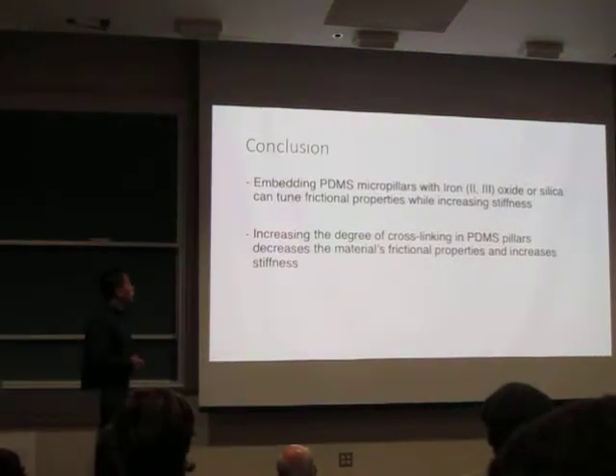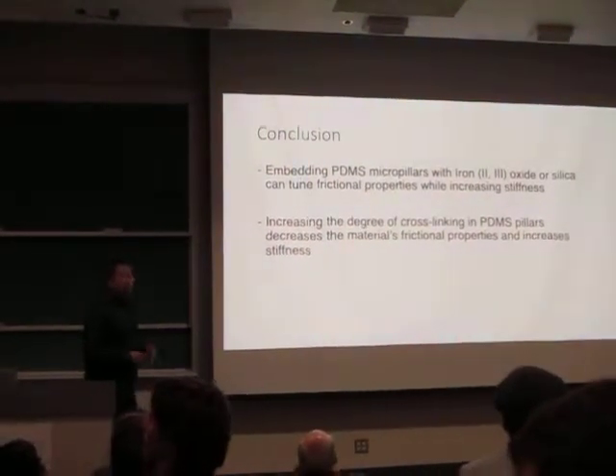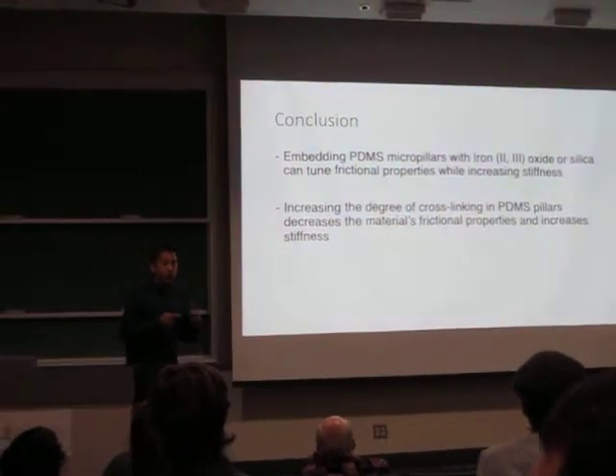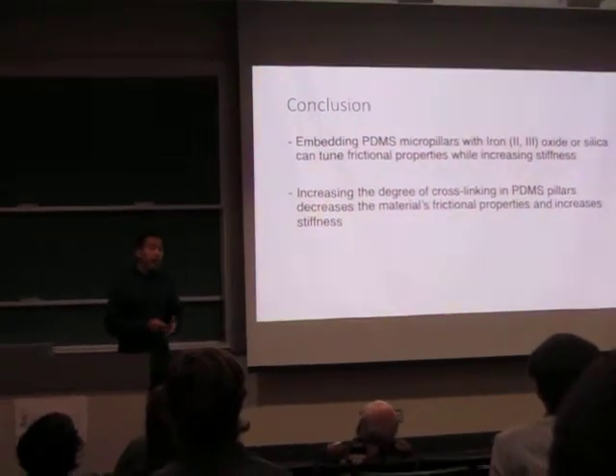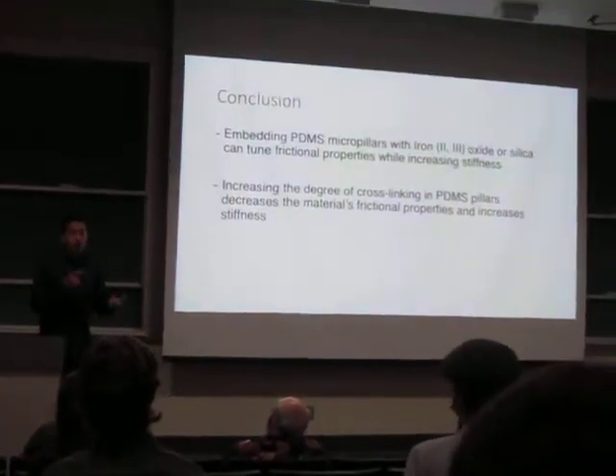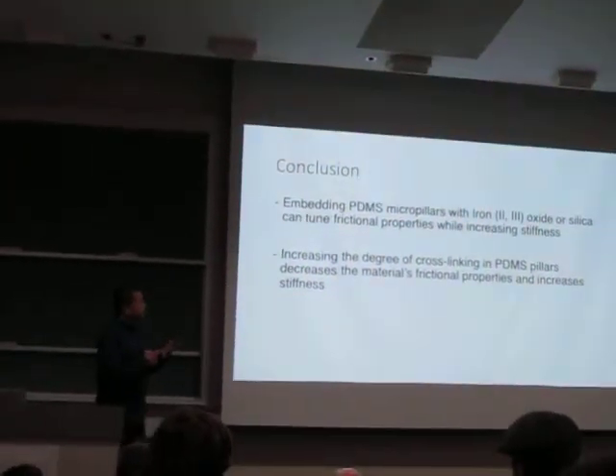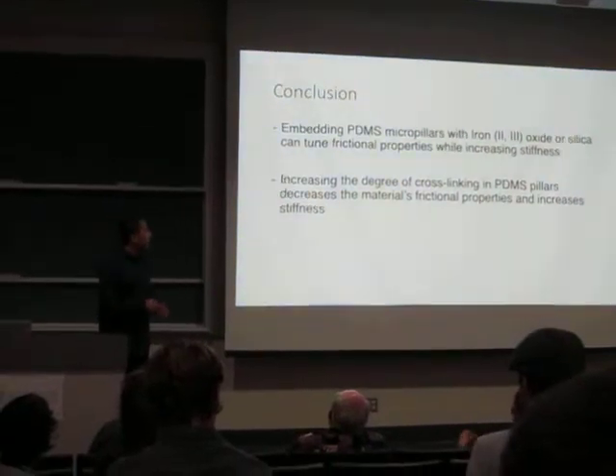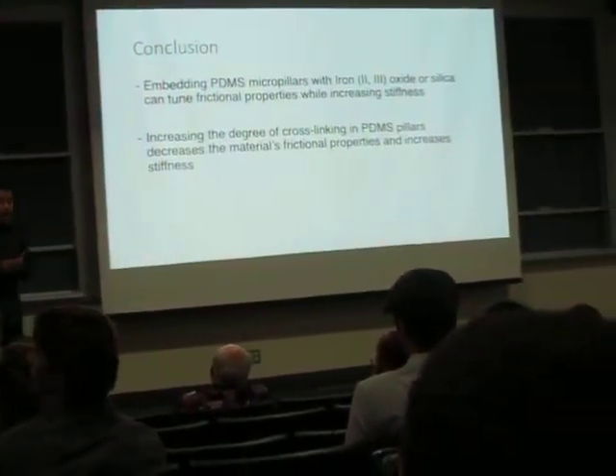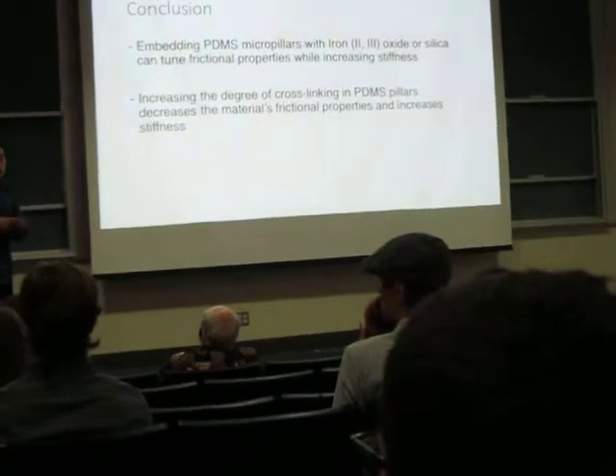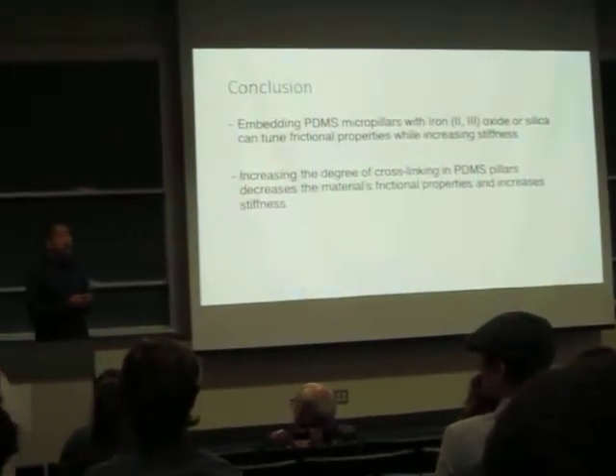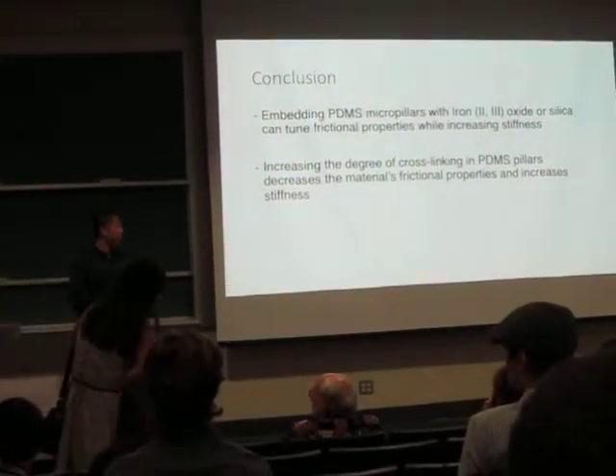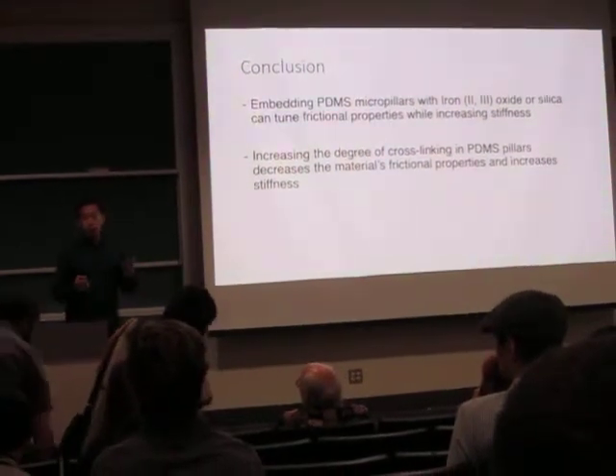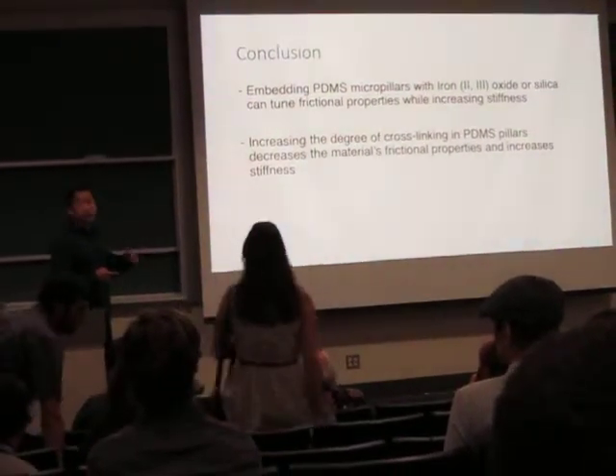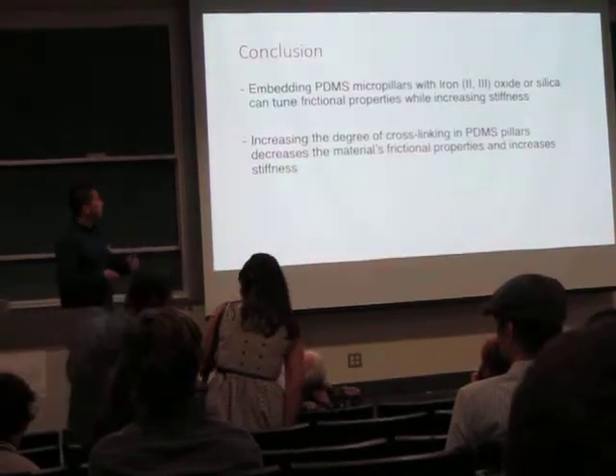And as a conclusion, there are 3 ways we can change the material strength and play with the frictional force. First, we can vary the amount of curing agent we use. Then we can also add iron oxide particles, which are micro scale, and we can also add silica particles, which are nano scale, and these 2 different size particles yield different frictional results.